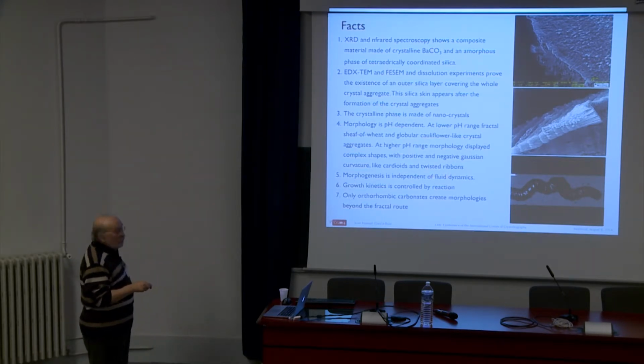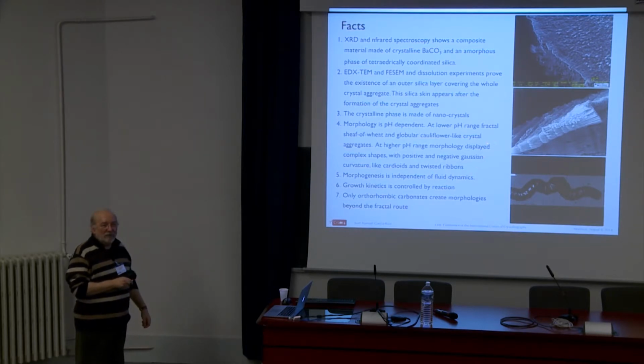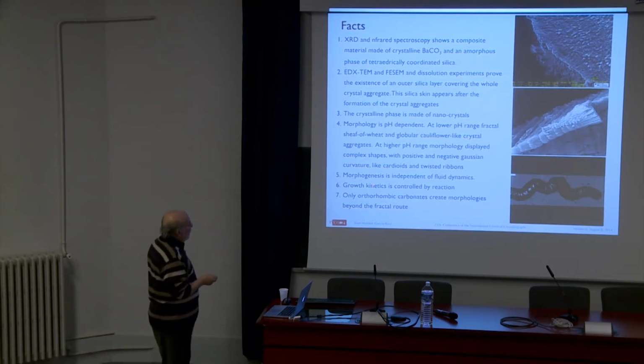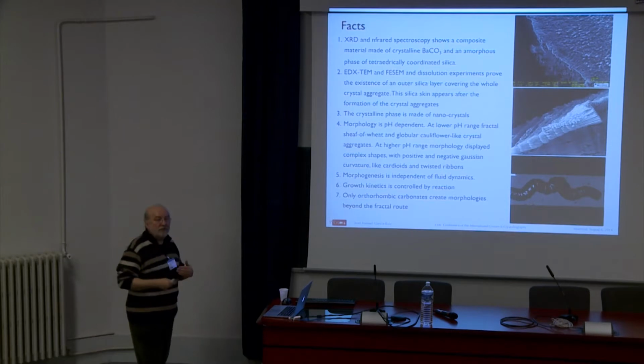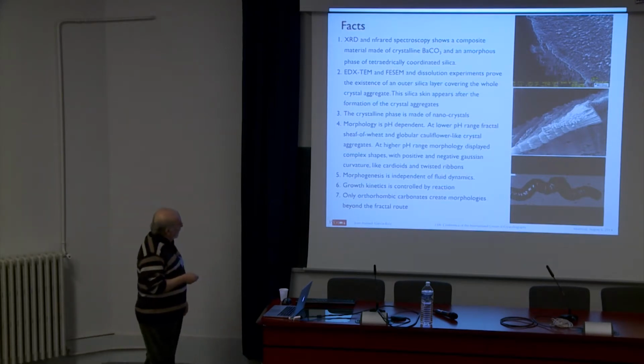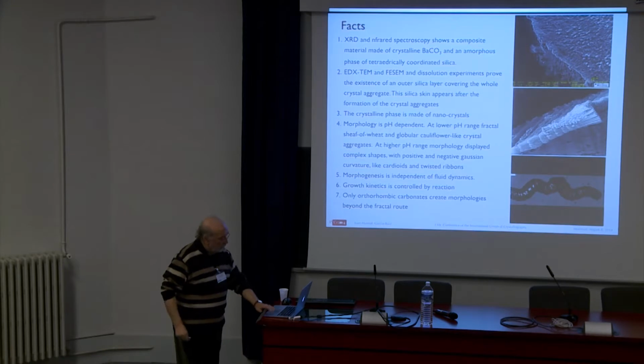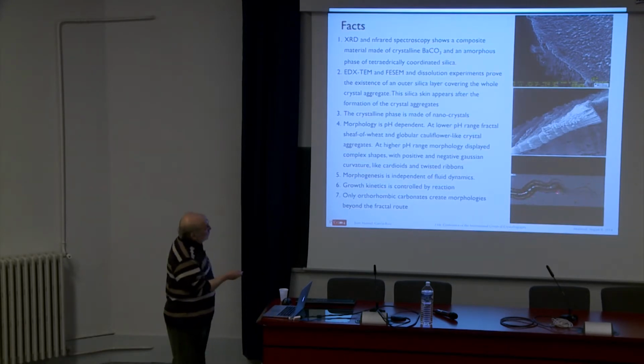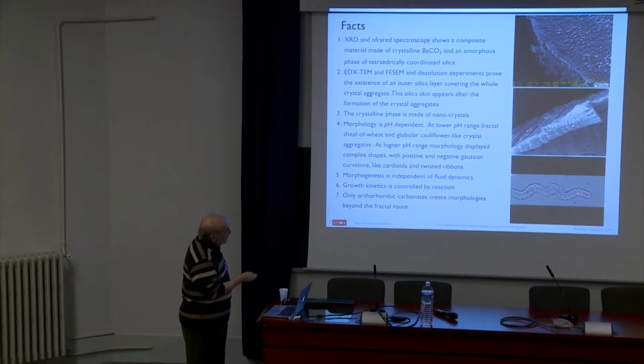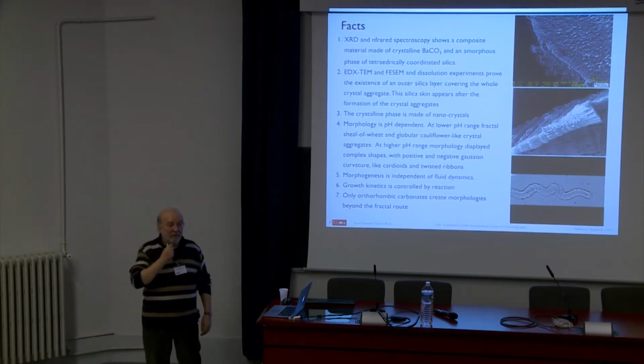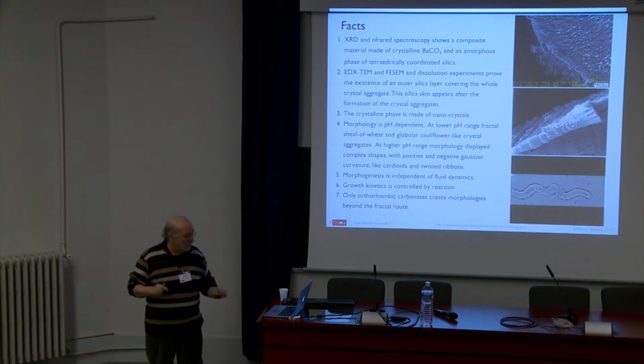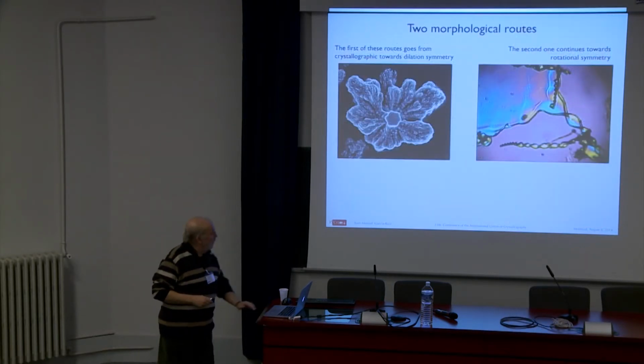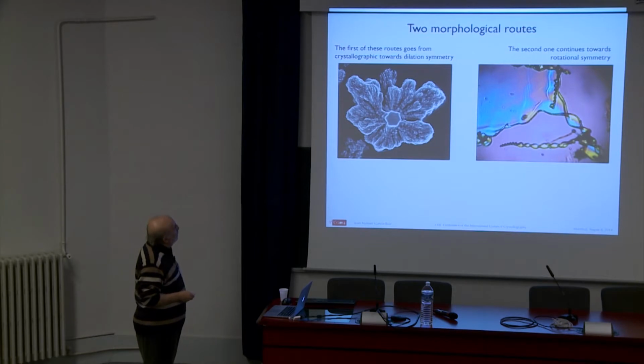So morphogenesis is independent of fluid dynamics. So no matter if you make this in gel, or you make it in solution, or you stir the solution at 300 revolutions per minute, still you have the morphology. It's not related with fluid dynamics. And growth kinetics is controlled by reaction. I mean, it's not diffusion controlled. As I told you, only orthorhombic carbonate creates morphology with these shapes. Okay? This is just to show that when you dissolve the carbonate, still you have the phantom of silica remaining, the hollow phantom of silica. You know. So there are two different routes to obtain this structure.